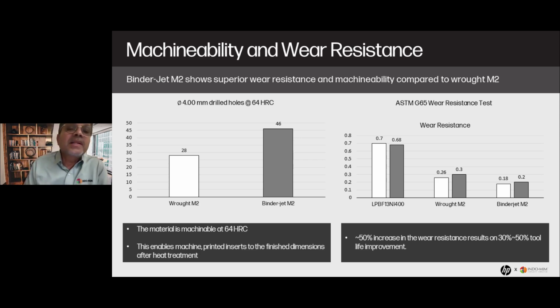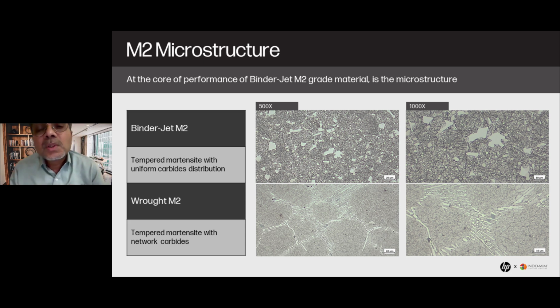So how are all these things possible? We talked about the material and the chemistry, everything is fine, but that still does not add up. Now, look at the microstructure here, because we start with a very, very fine metal powder, and we also achieve 99.5% minimum density. The microstructure that we are able to achieve on a binder jet 3D printed material is significantly superior. You get a very, very fine microstructure compared to a wrought material. And we all know, the finer the microstructure, the better the wear resistance, the better the machinability, and the better the life of the material that you produce with it.